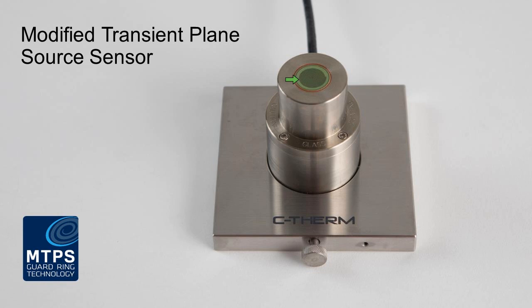The most important part of the sensor is that chipset that is sealed in the housing there with the RTV. It's comprised of an alumina substrate, and there are two circuits to the sensor. There's the central coil, which is the active sensor, and then there's what we call the guard ring around the contour of the sensor. Both of those circuits are electrically heated, and this is how the measurement functions.